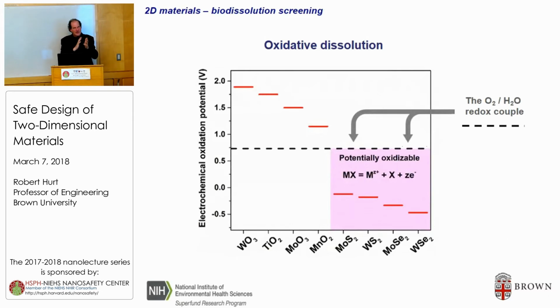And so most of our materials are, I think, too large for that to be a first-order effect. I could be wrong. Single-wall nanotubes are kind of outside that paradigm. They're so small, so thin, and floppy, not even long enough for the most part. So what I find interesting is people talk about high aspect ratio being a problem, and some single-wall nanotubes have enormous aspect ratios, but they can't present as stiff fibers because they're outside of that buckling theory. So this is a theory that more identifies the fiber-like, thicker materials as pathogenic.